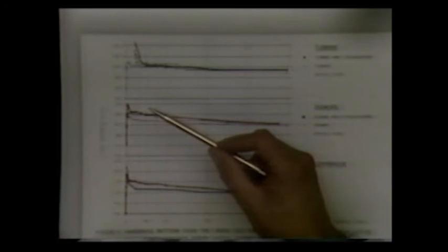As an example, the next figure shows the plain carbon steel 1060, where the initial condition indicates a significantly lower strength as a result of skin decarburization in the depth range of 12 thousandths to 15 thousandths. You can see it here. As in the case with grade 1035, turning results in near-surface work hardening to a depth of about 20 thousandths. That's the top diagram.